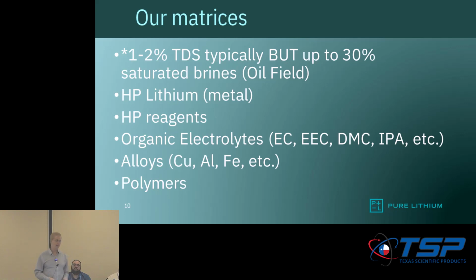And people will say, well, how do I know? Because you put lithium on one side, how do I know it's actually pulling lithium on the other side? And that was very good. So what we did was we developed an experiment where we would have lithium-7 in the electrolyte and lithium-6 in the brine. We'd make a synthetic brine. And what's unique about this is the ICP we have, and this is not common at all for ICPs, but the ICP we use can actually separate lithium-6 and lithium-7. So we did a calibration curve of lithium-6 and lithium-7, and you could actually see, as we applied current, the lithium-6 depositing after we redigested the cathode.